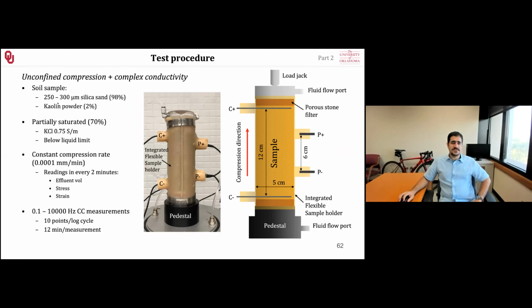We had a soil sample that was 98% silica sand, 250 to 300 micrometers. We added 2% kaolinite powder as well, because we needed a stiffer column that could hold together, because if you only have sand, it would just collapse when you partially saturate it. We partially saturated it below its liquid limit, so we would know this column would stand on its own, as you can see in this image. Then we compressed the sample very slowly, at 0.0001 millimeter per minute. We measured the effluent volume from these ports, the stress, and the strain, and at the same time we did the complex conductivity measurements.